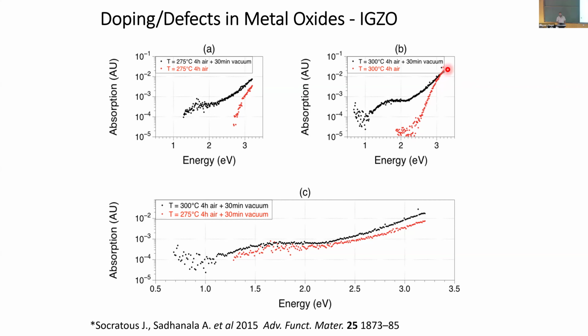You can see the red curve after the band gap, with the absorption dropping with some slope. The black curve is when we process additionally in a vacuum condition, where there is deficiency of oxygen—this can induce oxygen deficiency in your sample, and you can see new states come up in the absorption.